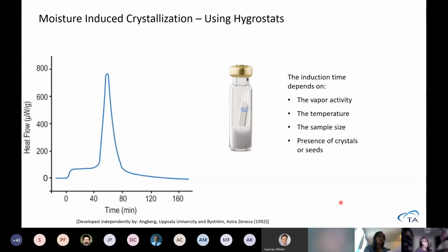The simplest way and the most, we'll say, high throughput method is, again, using a closed ampule and putting a small hygrostat in. So when you put a highly crystalline material here, if there is no amorphous content, you will not get a peak here. If you have small amounts of amorphous content where you induce the crystallization, you will put it into the calorimeter. You will measure first absorption of humidity or another vapor that will be absorbed to your molecule or your drug. And then once you have absorbed everything to lower the glass transition, you will have a peak of crystallization. If you get this peak, you know you have small amounts of amorphicity in your sample.